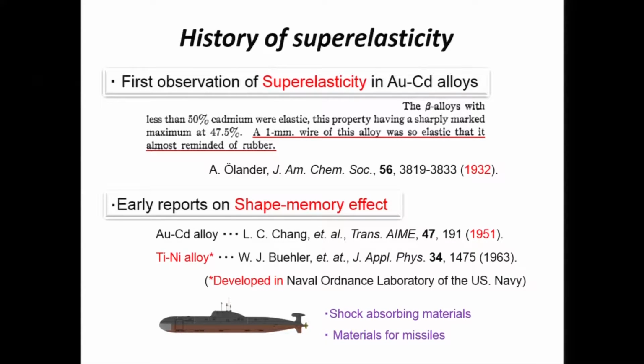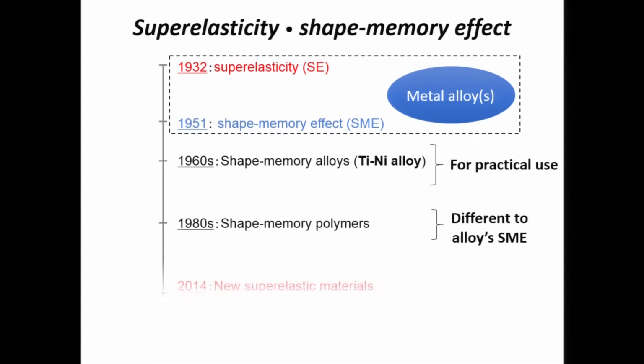This is the same kind of alloy. And then the titanium nickel alloy. This is a very useful alloy, and the finding of superelasticity and shape memory effect in titanium nickel alloy is very interesting. The titanium nickel alloy was developed as a shock absorbing material for submarines in the US Navy. So now I can say the science of superelasticity started in 1932. And in the 1960s, so-called shape memory alloys appeared.